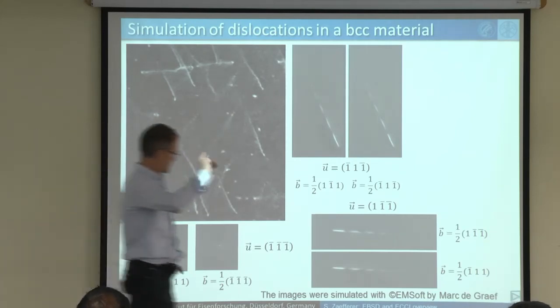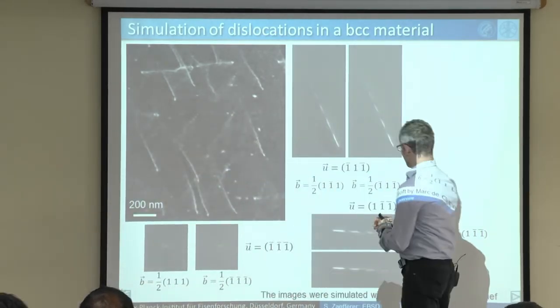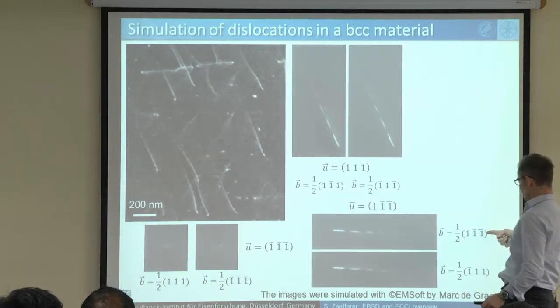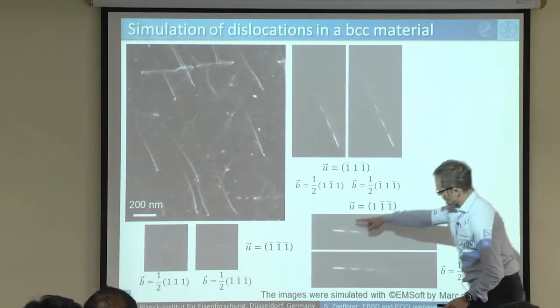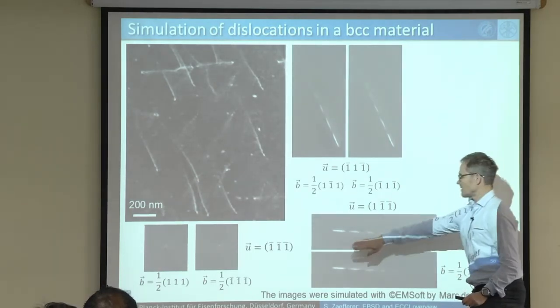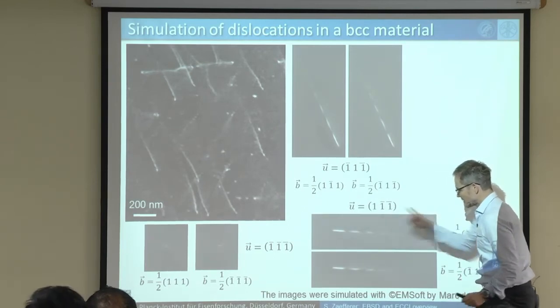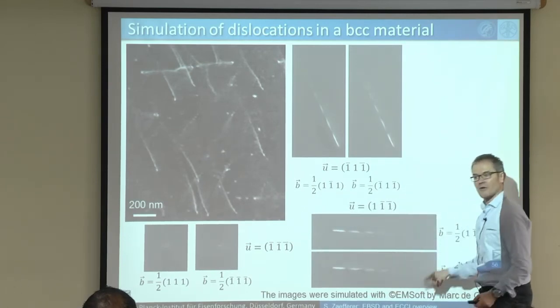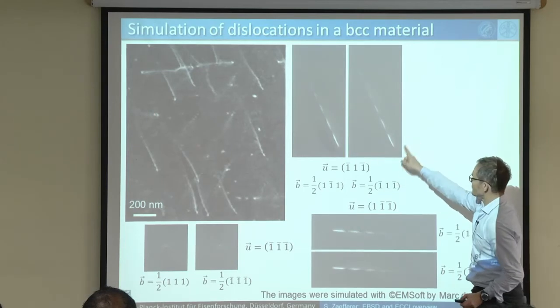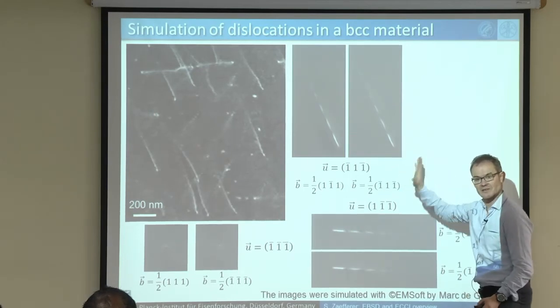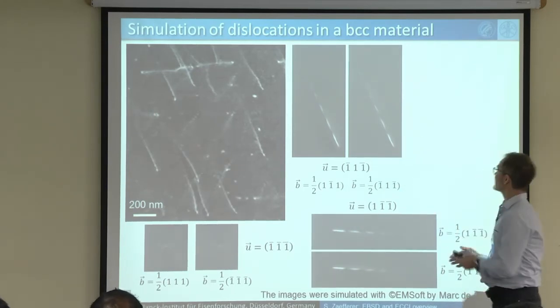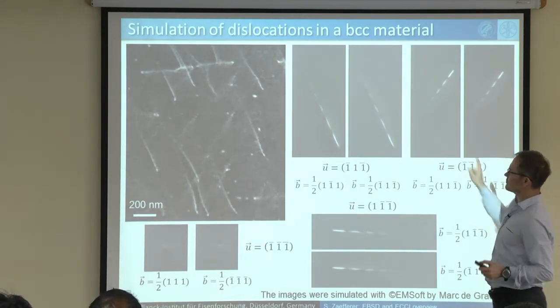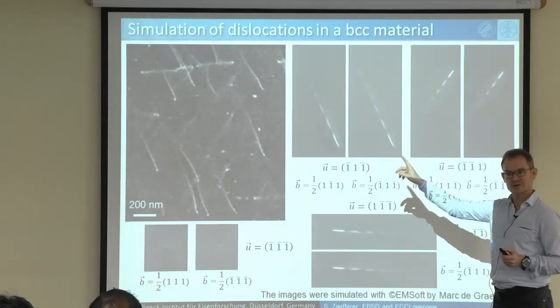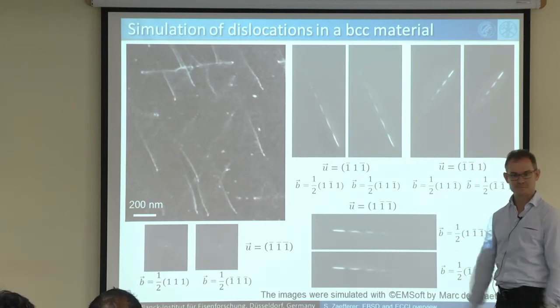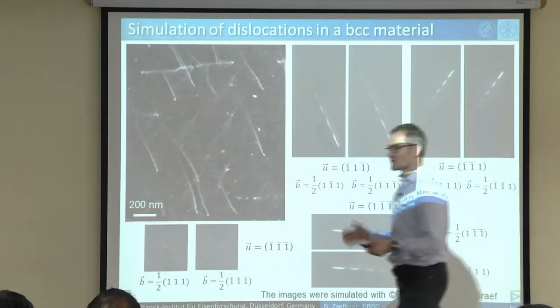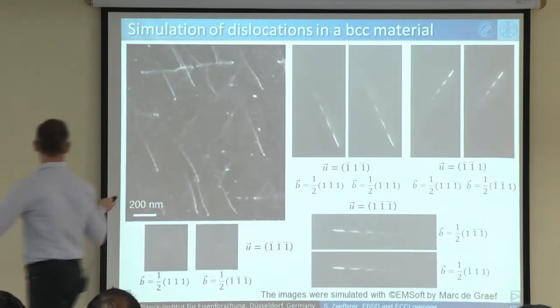Now, let's not take too much time, but you see if we take a positive or a negative Burgers vector, the oscillations invert. One oscillates up, down, up, down, up, down, and one oscillates down, up, down, up, down, up. And we see that for all these features here. If you look a little bit more in detail, you see it clearer. And from these calculations, we are now able to understand whether this is the same type of Burgers vector or whether it is dipoles. And this is a very beautiful application of understanding this microstructure.